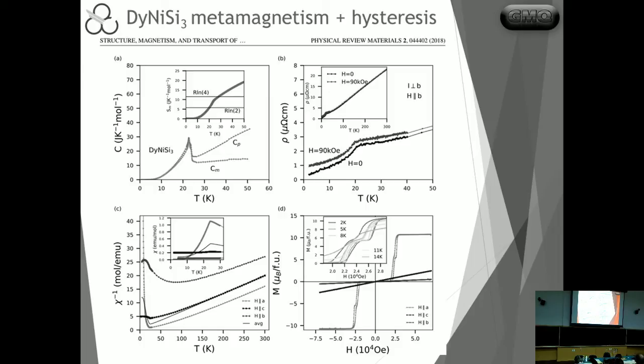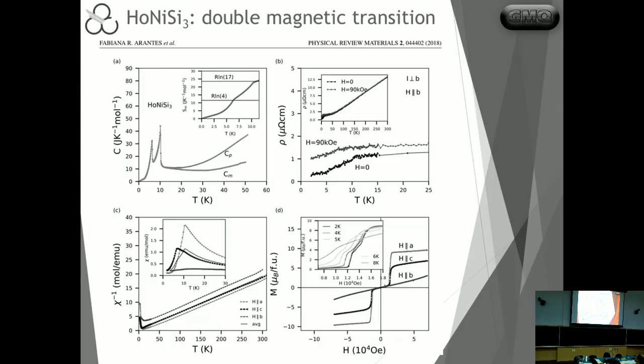And if we look here at the transition, there seems to be, although it's kind of hard to see in this case, there seems to be two peaks very close to each other here, so this might actually be a double transition. And we are especially suspicious in this case because as we move on to the next one, which is holmium, then we do see a very clear signature of a double transition in the specific heat. The first one reaches R log 4, and the second one here completes the full multiplet of the J equals 8 in this case.